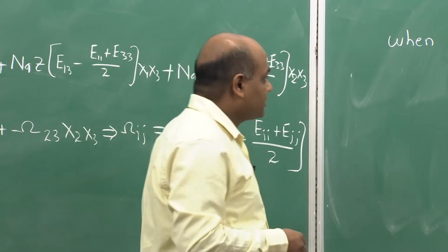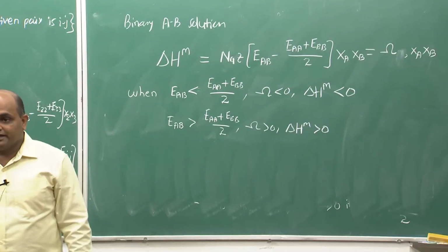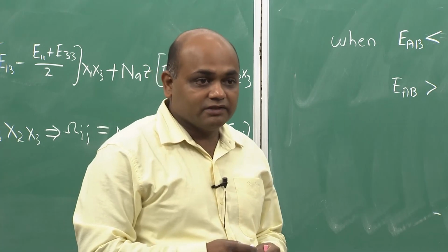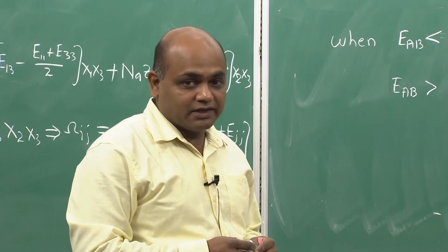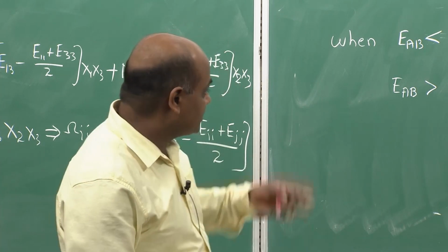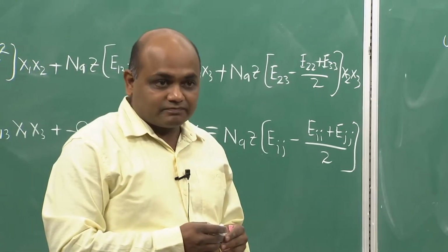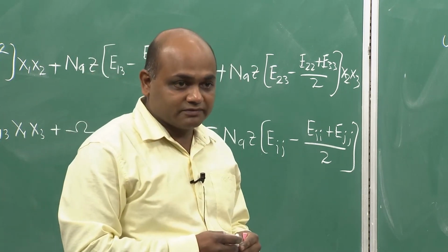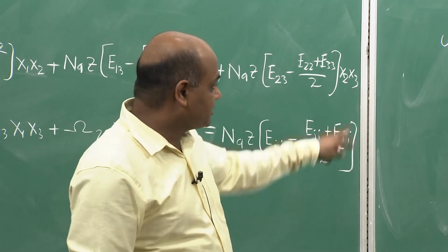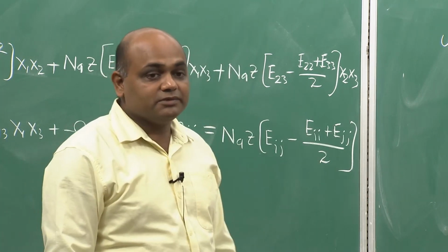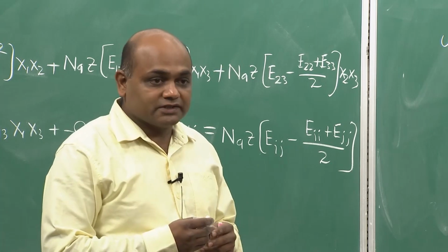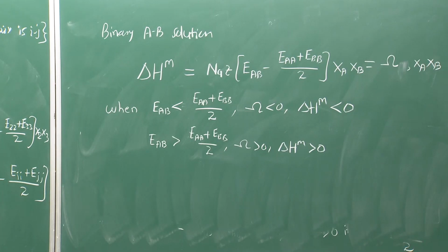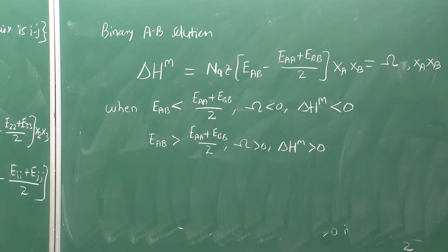Okay, so this is important. We went over this model in a little bit of detail because it is important to understand how the interactions between the atoms give rise to changes in the Gibbs free energy, basically changes in the enthalpies and entropies, because they also affect the diffusion, especially the cross effects, right. Because of these different interactions, the atom jumps will be biased in a multicomponent system, and so it is important to understand how these atom interactions affect the Gibbs free energy changes.